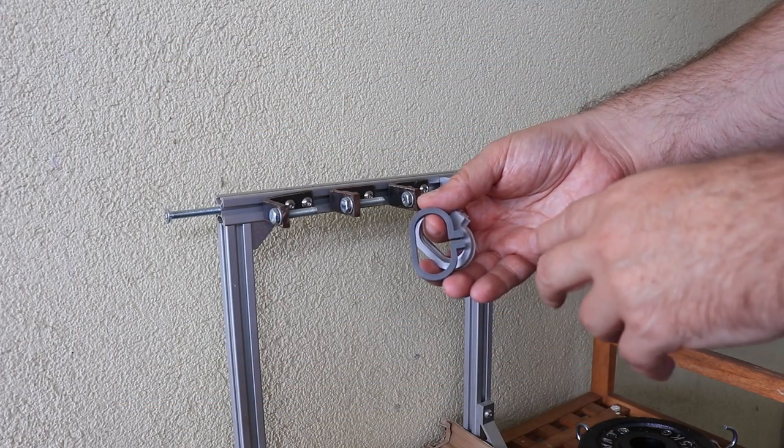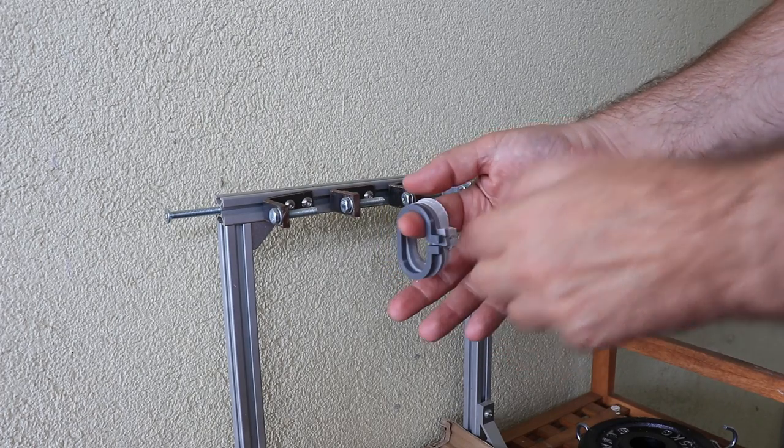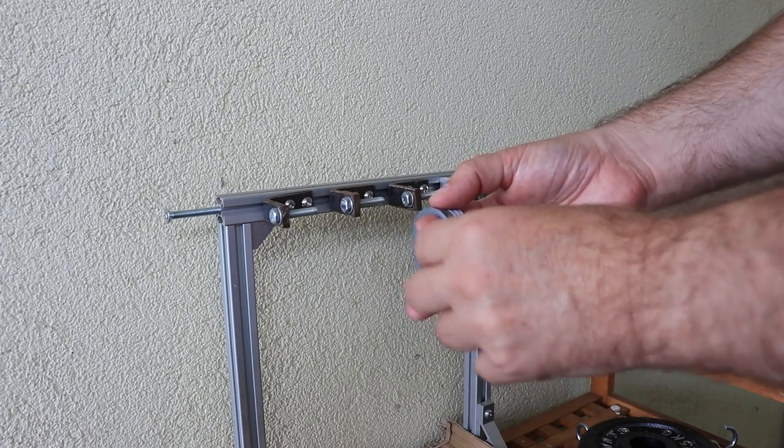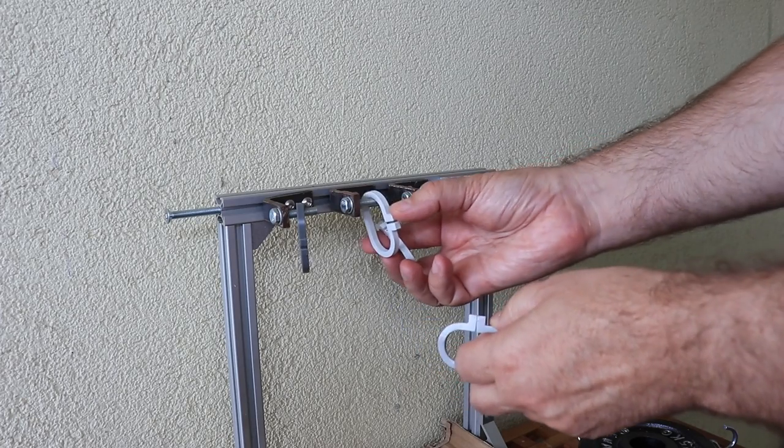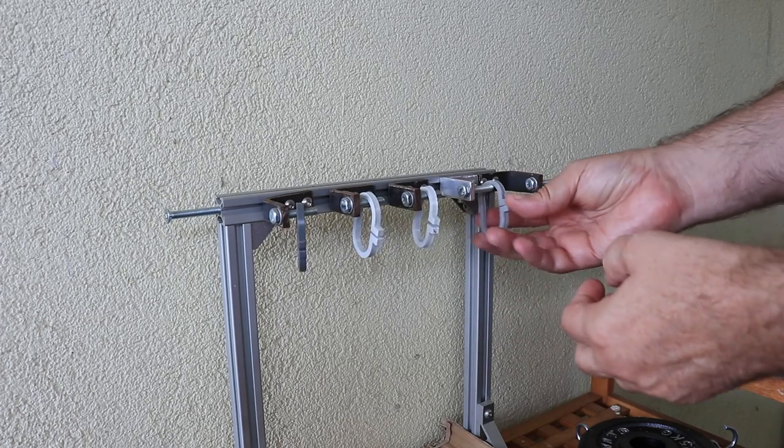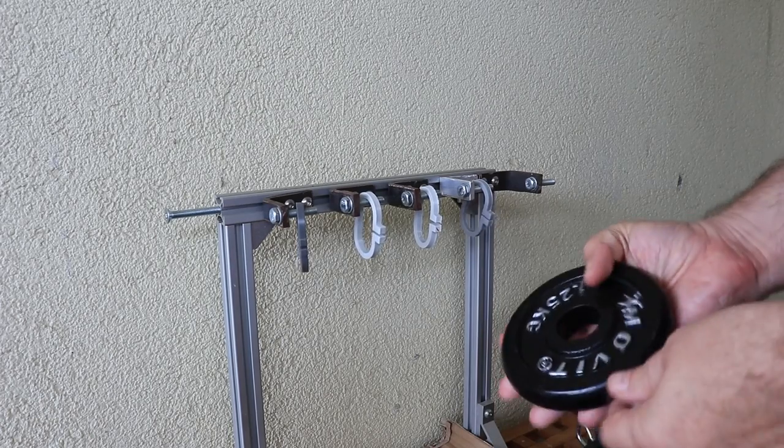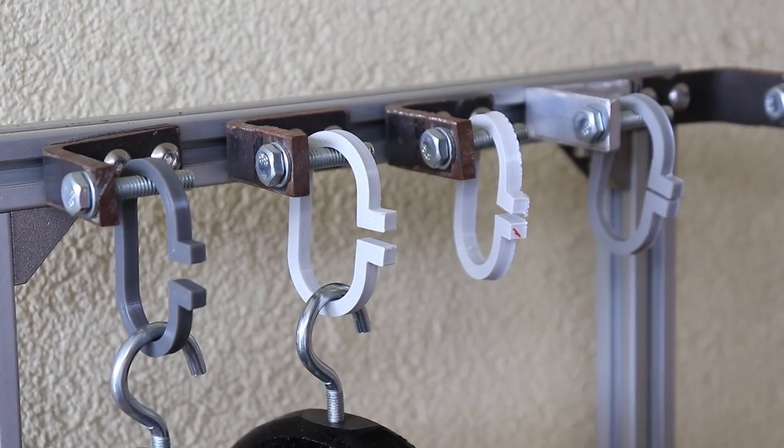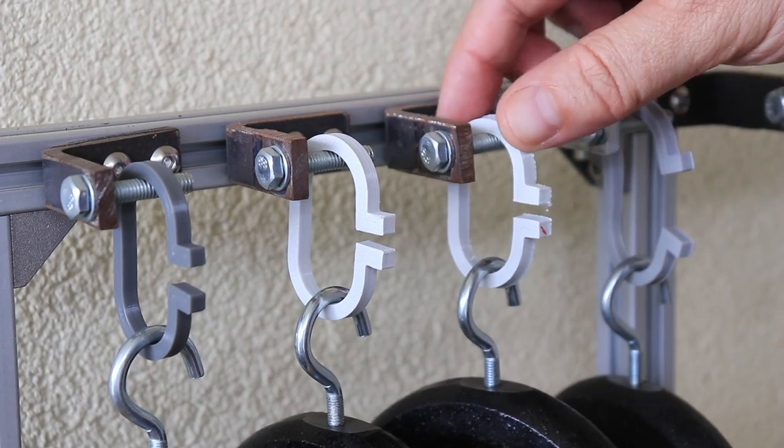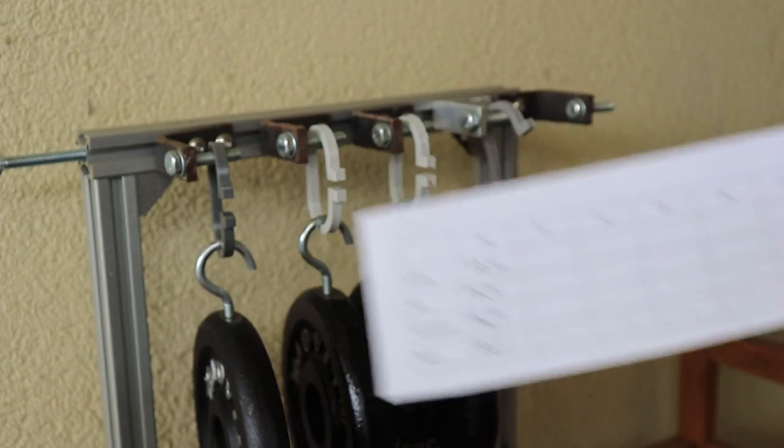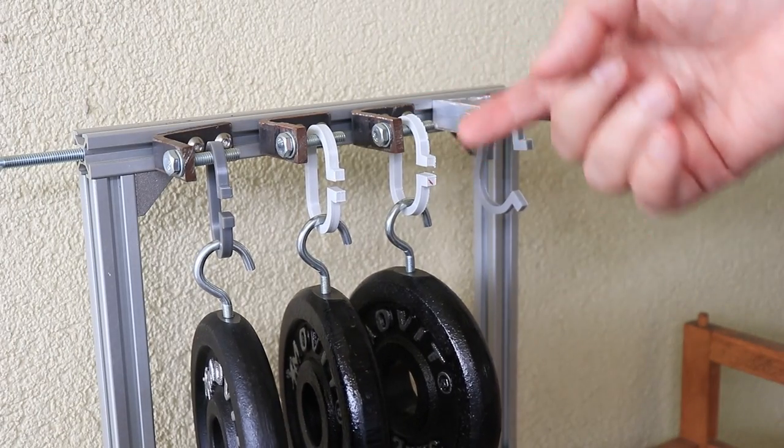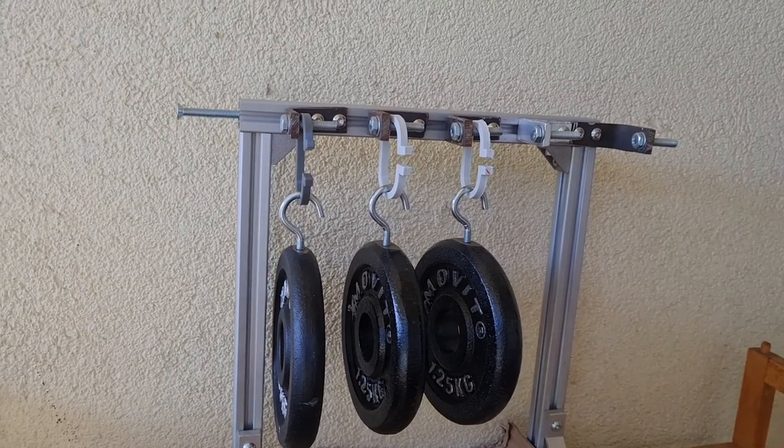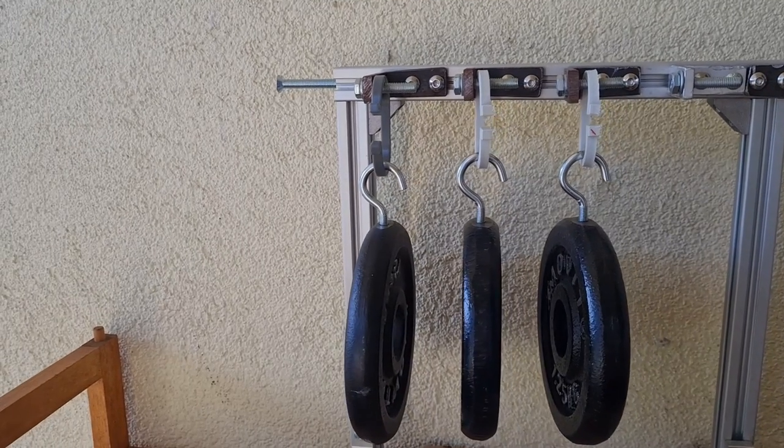And now my regular creep test where I am measuring the deformation distance between two reference surfaces under the constant load. And I have three estimates in progress at least we have some comparison between them. So this one is the easy ABS, this is the PLA, this one is the annealed PLA, and this is some resin material. The load will be 1.25 kilograms as always. I measure the distance and tomorrow I will measure again to see what is the additional deformation. In the meantime the weight from the resin fell down after 10 minutes. But so far the smallest deformation is on annealed PLA. I measure them daily and this is the deformation after 5th day. And very minimally but the smallest deformation is on annealed PLA.